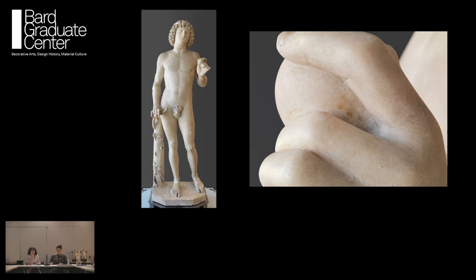The sculpture was also examined to determine whether it might have been partially gilded, as we know many Renaissance marbles were. The Vendramin Monument, from where our Adam comes, has several areas of gilded decoration. While no gilding was discernible on Adam, traces of a reddish-brown material were found on the fruit held in Adam's left hand. This material was analyzed by Federico Caro from our Department of Scientific Research at the Met, and it was found to contain clay minerals and iron oxides, and that's consistent with bole, a preparation for gilding. So it's possible that this area of the sculpture, at least, was gilded.